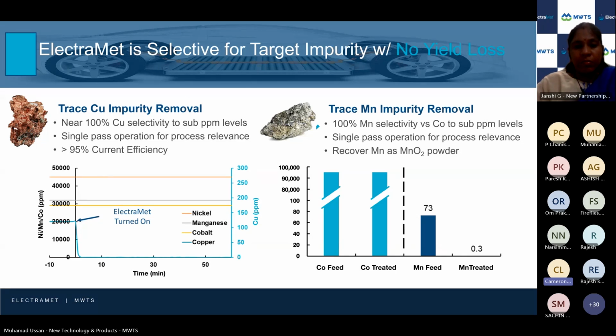So that means all the energy going into our system is being used to remove the copper and not other parasitic reactions. And on the right, this was a sample from a client who has the final cobalt SX product stream, right? They want to sell this, but the manganese was too high. So traditionally they would add what's called Caro's acid, so sulfuric acid, peroxide, other chemicals to force oxidation of manganese and precipitate it as MnO2. By doing that, you are now going to input stuff into your product stream. You usually have to adjust the pH as well. So all these factors result in the yield loss of that cobalt, and also adds on more processing steps, which increases the cost of hitting that high purity battery grade cobalt.